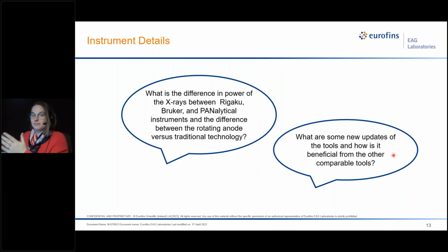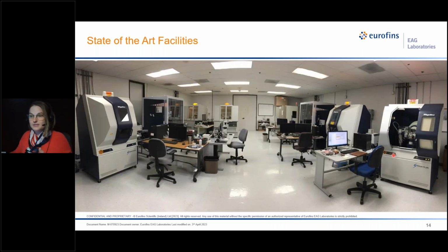So now that we know a little bit about X-rays and what a diffractometer is going to give us, a lot of people wanted to know details about our specific instruments and some differences between them because different companies make different instruments. And we actually have 9 diffractometers in our lab from 3 different companies. Most of our instruments use copper radiation, but we do have one that's cobalt. Cobalt is very good for iron-rich samples, which fluoresce strongly, so it can lower the fluorescent signal so that you can see your diffraction better.